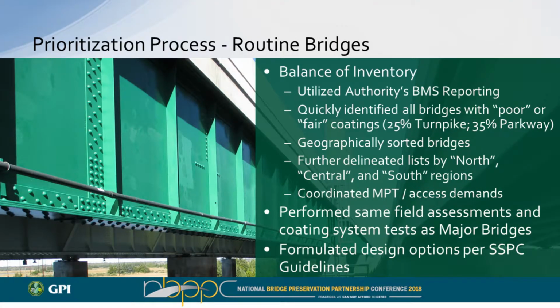So even though we'd be addressing one that's satisfactory or good, at least we can leave that area and walk away and be done, hopefully for 30, 40 years before we needed to come back. We did the same field assessment, so we went back out. We did the coatings testing, the integrity testing, the adhesion, the pull-off, the gauge to determine how many coats of paint were there, and sent the samples off to the lab to see what we're dealing with, the heavy metals or the lead-based coatings, and then proceeded to design, again, with the SSPC requirements in the background. Okay, so now we have our structures identified.